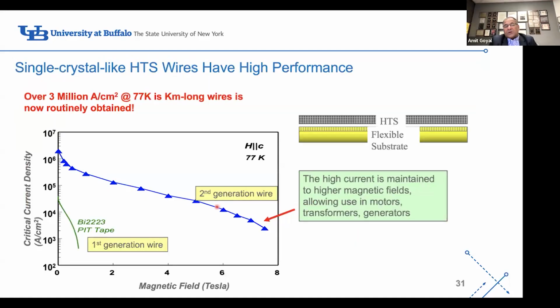So I had showed you in one of the slides previously that this blue curve is what we needed. 3 million amps per centimeter squared, kilometer-long wires. So this blue curve is actually also, we've gotten better. So this is the blue curve starting at 1 million. What we now get for the superconductors and RABiTS routinely is 3 million amps per centimeter squared at 77 Kelvin in kilometer-long wires. So this is how we achieve it.